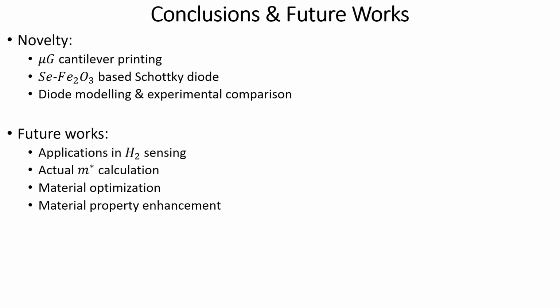Future works involves applications in gas sensing. In fact, we have carried out the experiments required for this and have obtained promising results. We also require to calculate the actual M star or the effective mass for the Fe2O3 material. We realize that we have taken the effective mass of a different material for the calculation of this selenium doped Fe2O3 based Schottky diode. However, we expect the effective mass of both the materials to be of the same order and therefore can be approximated. However, further experimental data is required for computing the actual M star for this particular material so that it can be used for further applications.